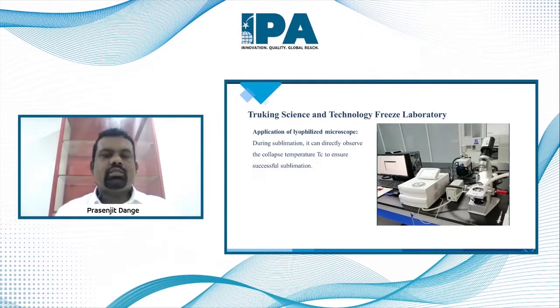And by applying the vacuum, the temperature is gradually increased, which is known as the drying process. Then the samples start drying. During this temperature ramp, the sublimation front is observed and recorded through a microscope. Now, changes in the dried layer can be used to determine the state of the system, whether amorphous or crystalline, and the collapse temperature of the sample can be determined with this. So this is one of the instruments which can be used for determining the collapse temperature. Next slide.